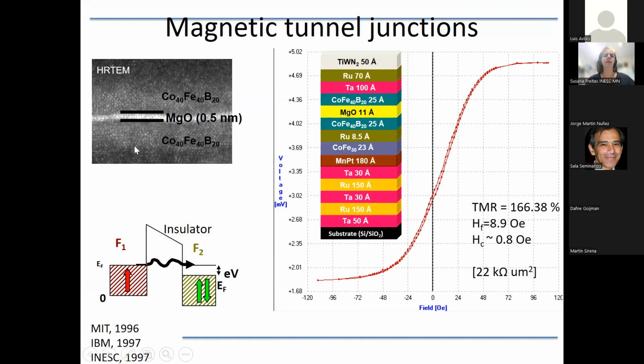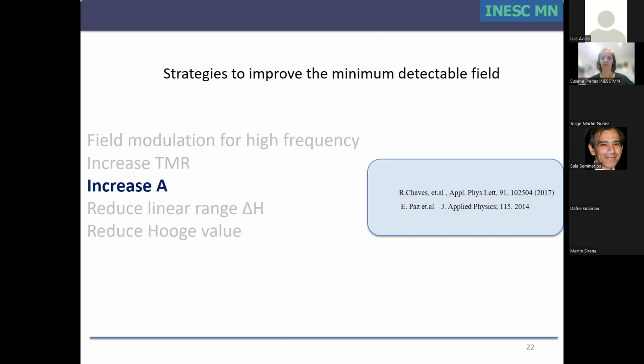So we have good magnetic materials, a very good tunnel interface, and good control of the magnetic properties, and then at the end we provide a sensor that changes the voltage as a function of the magnetic field. Here is an example of an experimental result from one sensor that shows a tunnel magnetoresistance of 166% using an MgO barrier. This is an example that can be achieved in the lab, normally at room temperature, and it is a standard value currently obtained in a very large number of labs.